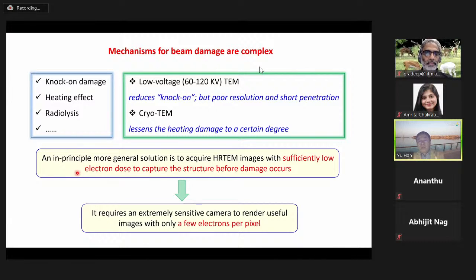So we decided to develop a low-dose technique, not low voltage, not low temperature, but low dose. Well, this idea sounds easy, but it's very hard to realize. If you recall the electron dose a MOF material can withstand, only 15 electrons per square angstrom, then you may realize that imaging with such a low dose at a reasonably high magnification actually requires a very, very sensitive camera to render useful information with only a few electrons per pixel. Okay. A conventional CCD camera cannot do the job.